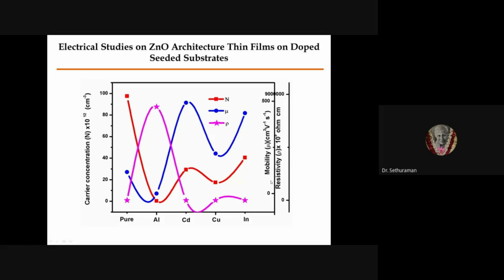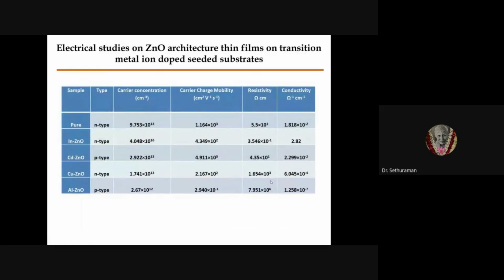The pure one has a very high carrier concentration, but mobility is low. After doping with different metal ions, we found that the carrier concentration decreases and mobility increases. The same feature is observed for all the doping cases. We found the carrier concentration, charge carrier mobility, resistivity and conductivity of all the doped seeded substrates.